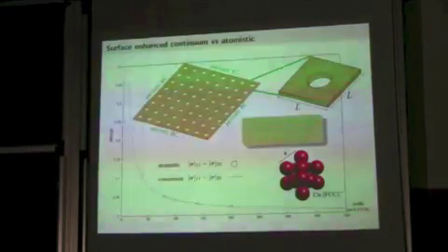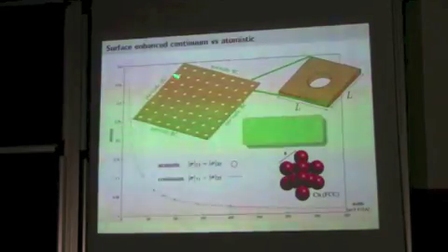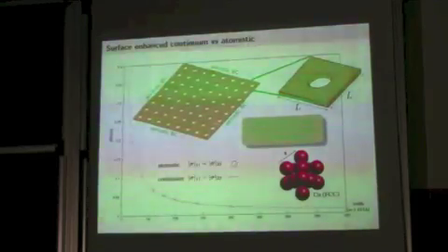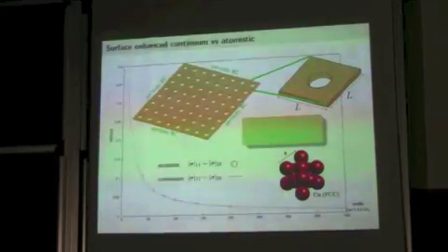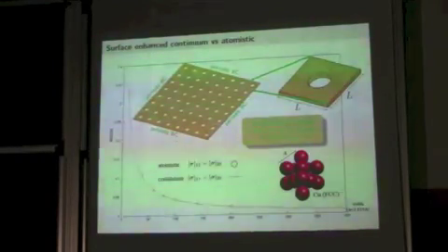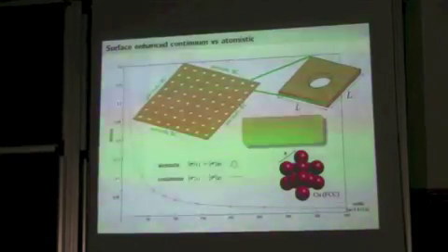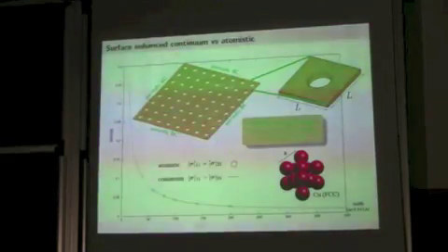If now you look at the same simulation, so you think that you have this material, you have this structure sort of repeated periodically, you can calculate the properties of the material by atomistic simulation, and you can compare it with this additional energy that we get from our surface modeling. So this is what we did. This size effect that you see generally with atomistic simulation, again, I repeat, it's not there in our classical first order continuum mechanics, but here we can pick it up easily.